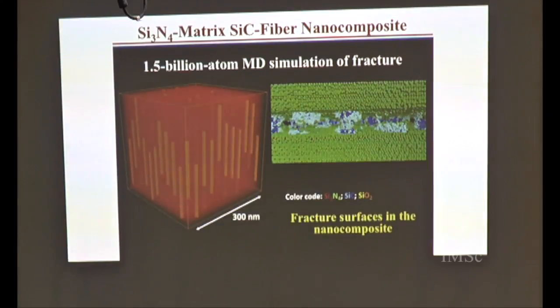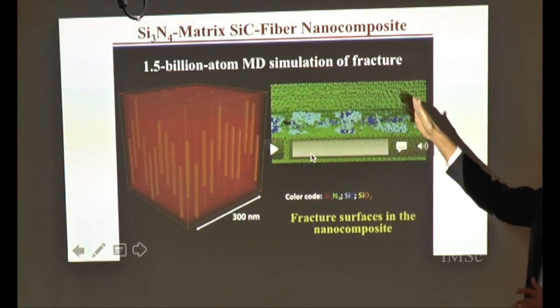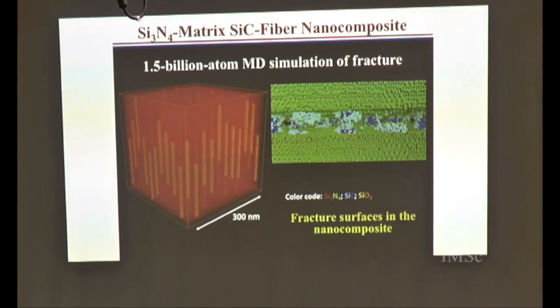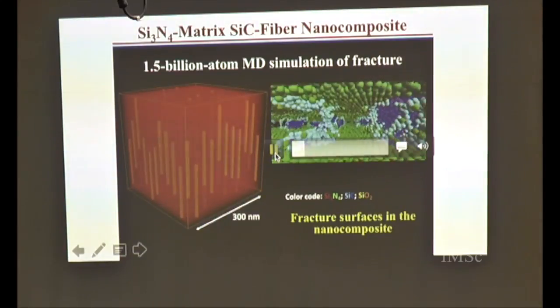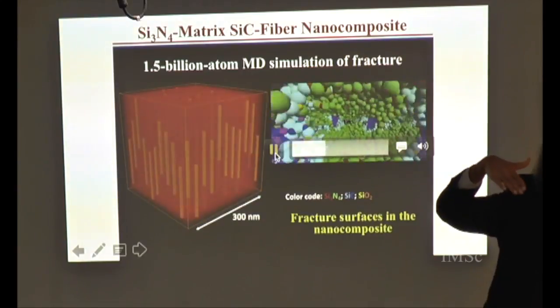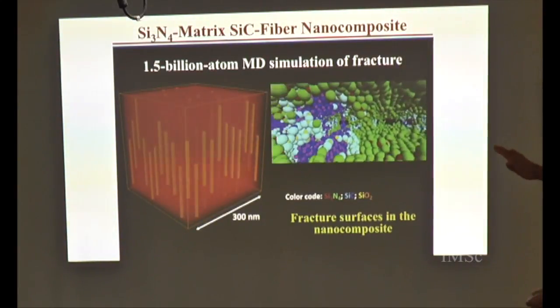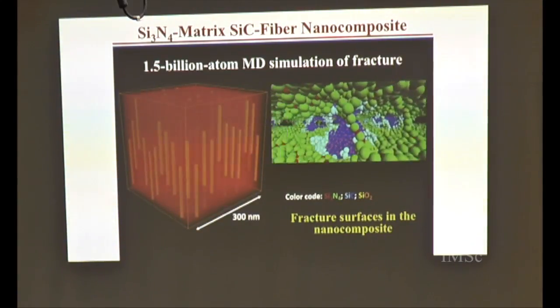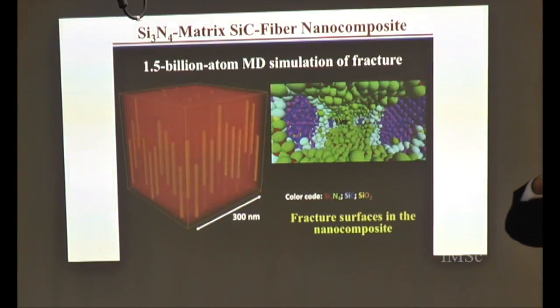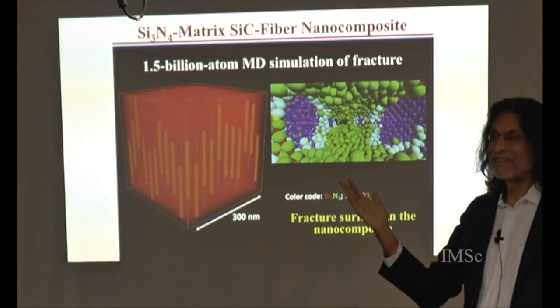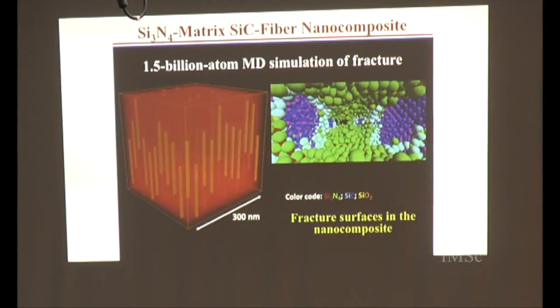And let me end my talk by showing, first let me show you this, and then I'll tell you something we find very interesting. So this is a simulation in which we have silicon carbide fibers embedded in silicon nitride. The nice thing about these simulations is you can actually go inside your simulation and look at fracture surfaces. So now this is a simulation where we can actually go inside the fracture surface and examine it. On the screen it is not as impressive, but we have this three-dimensional visualization. So we can actually walk into this fracture surface and we are totally immersed in it. And this is a huge visualization facility we have in our lab.